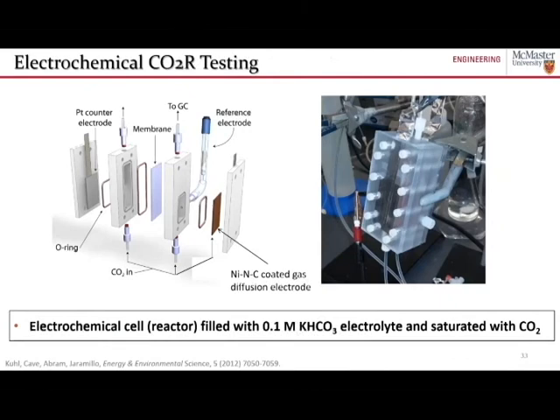So we wanted to take them and test them for their activity towards the electrochemical carbon dioxide reduction. We had this custom designed cell that we would fill with 0.1 molar potassium bicarbonate, and then we would saturate it with CO2, constantly flowing CO2 through the electrolyte, as well as behind our electrode that had our catalyst on it, so that we had a gas diffusion electrode where CO2 was accessible to the catalyst both in the gas phase and the liquid phase.